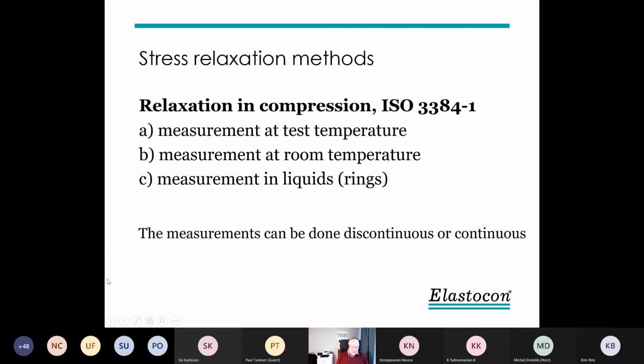And then the test jig is put into an oven for aging and taken out, cooled down, measured again at lab temperature. And this was the way of doing it originally before we had more of these continuous stress relaxation instruments. The method A and B gives different results. In B, we also have the effect of the rubber shrinkage and expansion when we change temperature.